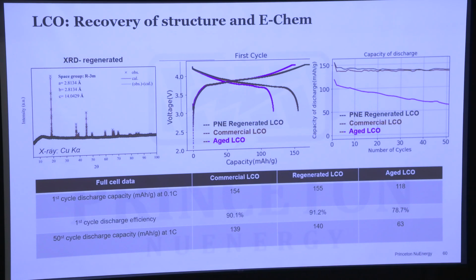And what they did was this kind of XRD measurement, about how much of the lithium can be removed, and they regenerated a beautiful XRD signal. And this is a comparison of the battery voltage over cycling. You can see the aged batteries have lithium cobalt oxide, LCO, which is typically used in your iPhone. You can discharge the aged batteries, and you see the capacity is 100, 110, 120. The new ones should be 150 and 160.